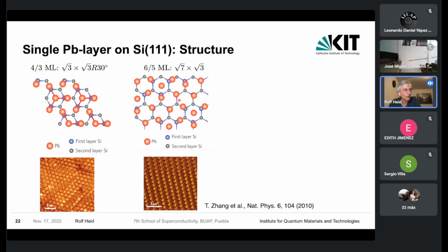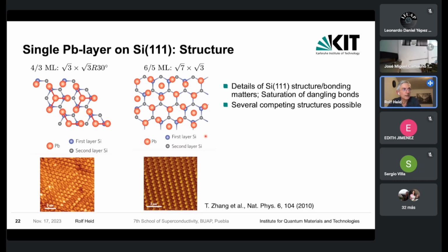There have been other structures observed of different types and also of different coverage. So indeed, this 4/3 monolayer means that you have 4 lead atoms in the same area as 3 silicon atoms. And the density of this layer is actually even larger, by 5%, than the density of lead atoms in a 111 layer, for example, of bulk lead. And of course, for this type of structures, the details of the bonding to the surface really matter. In particular, this bonding should capture the saturation of the dangling bonds of this silicon 111 surface. And as I mentioned, one can have several competing structures which may have different properties and stability.